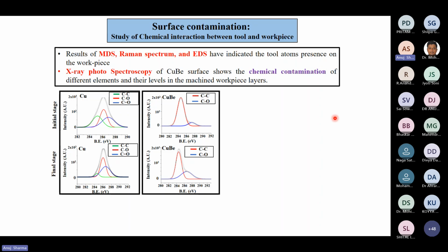So after that, I analyzed the surface for any chemical contamination. Basically, X-ray photoelectron spectroscopy on the copper beryllium surface was carried out, and for copper and copper beryllium the following peaks were seen: 284.8, which corresponds to the carbon-carbon peak; 286, the carbon-oxygen peak; and 288, the C double bond O peak. So these 3 peaks were observed.